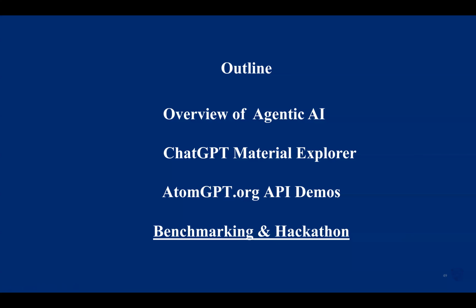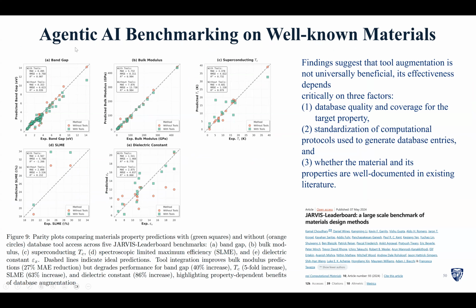So now how do you benchmark this agentic AI? And that leads to the last section of this talk. This is very difficult. As we mentioned, agents have LLMs, so we can benchmark LLMs. We have APIs, so we can benchmark APIs. But together we can also benchmark for well-known materials. For instance, we took the electronic band gaps, bulk modulus, superconducting transition temperature, solar cell efficiency, and dielectric constants from the JARVIS leaderboard benchmarking platform, experimental values, and did this really interesting test where we had predictions from the base GPT OSS model and the agentic models, so with tools and without tools.